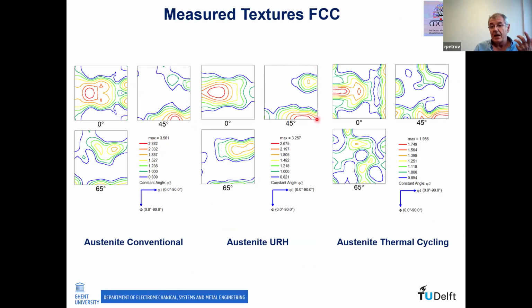This is a real measurement. And here again you have this one plus Goss. To get the Goss texture component in this story with transformation, you should have recrystallized austenite. This is the clear indicator for transformation of recrystallized austenite, at least for what we know until now. This is the story with the texture and microstructures in this steel.